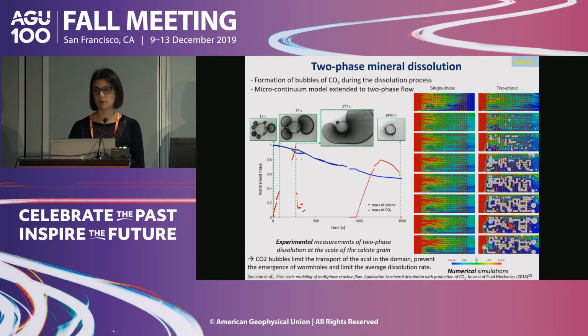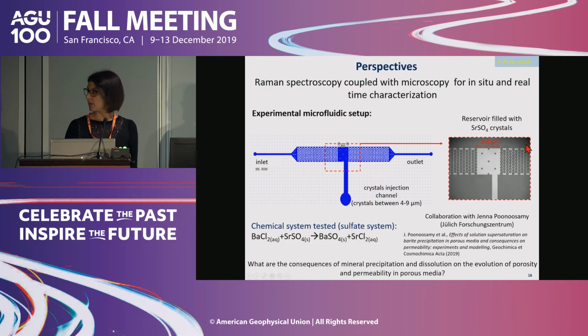So one conclusion of this work is that in the case of these two-phase dissolution, the Péclet-Damköhler diagram should probably involve one other parameter, like taking into account the solubility of the CO2. So now I want to show you some ongoing work to show you that we can even get more details into the reaction with microfluidics experiments.